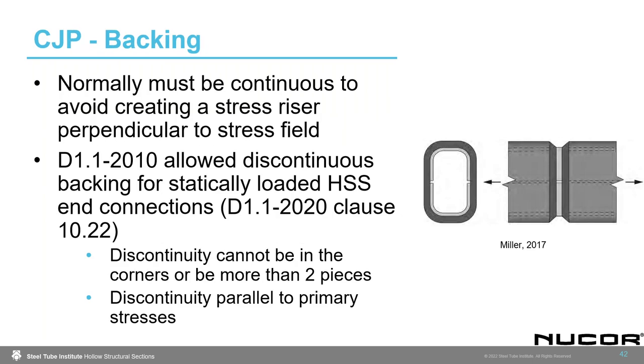For the backing, if we're allowed to back the weld, and so we can use that, normally, I'm sure you're familiar that D11 says that the backing has to be continuous. We're trying to avoid stress risers in the backing by specifying that. However, in 2010, D11 allowed discontinuous backing for statically loaded HSS end connections. So that one application, you are allowed to have a discontinuity in the backing.